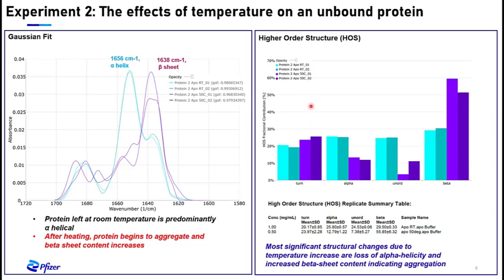To the right, our higher order structure bar graph is shown, and you can clearly see that the most significant changes in protein structure due to the increased temperature are again loss of alpha helicity and a gain of beta sheet content, indicating aggregation has occurred.